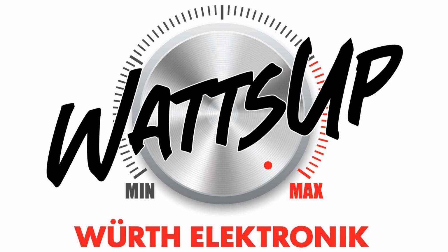We can actually deduce the role of each coefficient of the complex permeability based on the impedance formula shown on this screen. We see that the inductive reactance is dependent on mu prime, and the resistivity is dependent on mu double prime. So the same component can be used for either filtering or for inductance, depending on the frequency that it is used. Just so you know, you can refer back to the crossover frequency discussed earlier in order to identify those frequencies.